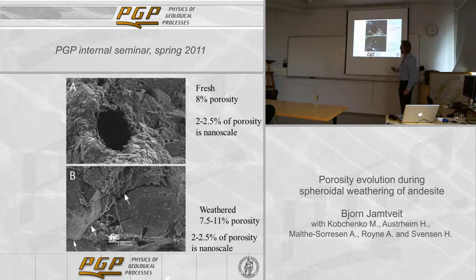But around the pores where we have growth, we often start dilating grain contacts. For example, you can see a fracture or a dilated grain contact between this feldspar grain and the surroundings. There is a crack, and there are narrow fractures all over the place in the altered rocks in between the macroscopic fractures. There's lots of microfractures.